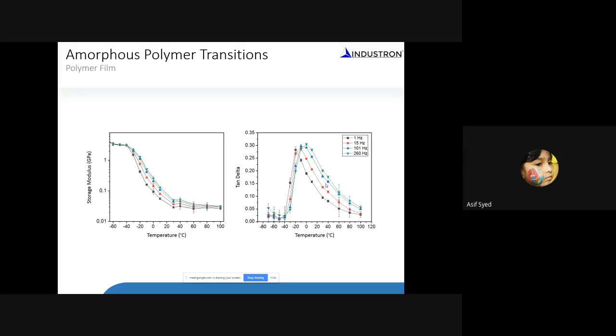So we can do that, and we can also measure the tan delta. Tan delta is basically the ratio between the loss and the storage modulus, and you can measure it as a function of temperature. You can go at lower temperature as well as higher temperature. So it's useful for polymer material characterization as well.